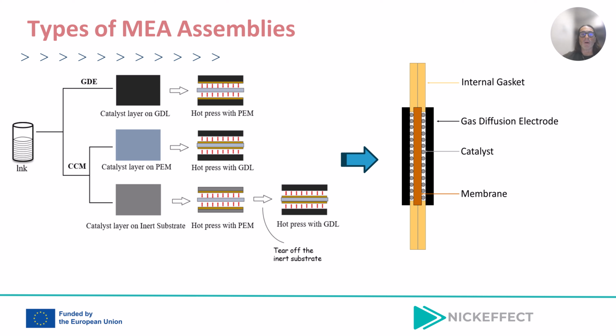Next, we have the catalyst-coated membrane, or CCM, configuration. Here, the catalyst is applied directly onto the membrane itself. The membrane is then hot pressed with the gas diffusion layers, GDLs, on both sides. This configuration offers excellent control over catalyst loading and uniformity. The third configuration involves applying the catalyst layer onto an inert substrate. This layer is then transferred onto the membrane during the hot pressing process. This method is useful in certain specialized applications where precise control of the catalyst layer is needed.